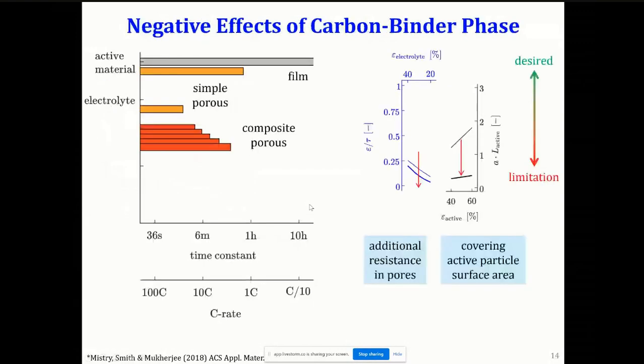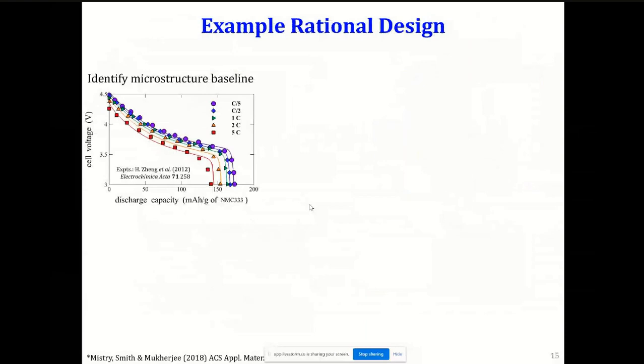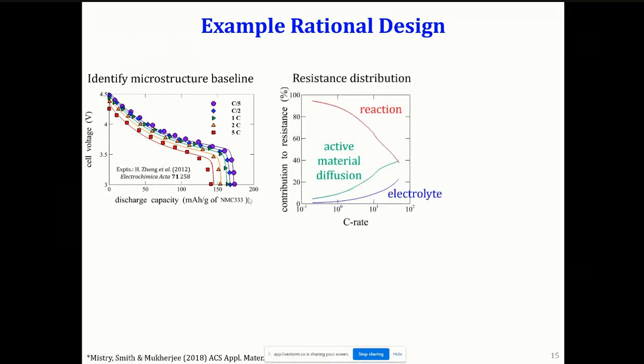Now, what's the advantage of having this information? The advantage is that now you can systematically tune your electrolyte for different applications. Let me illustrate that by an example. For example, we start with this baseline recipe, and the way we go about it is, once we have the electrodes, we know what the composition is. So we know the volume fraction of different phases. The information that we don't have is the actual area and the actual tortuosity. So what we do is we use the appropriate porous electrode theory model to get a fit with the experimental data. The dots are experimental data across various rates. And then from there, once we have this theoretical information, we can construct these resistance plots.